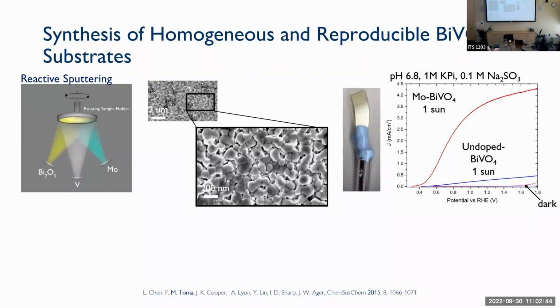So if you don't have any doping, you have kind of a very sad and flat curve. But then if you dope the material with molybdenum, then you see a shift in the onset potential. And this is really important because it tells you the operating voltage of the material. And then you see also an increase in the current density, which is also another factor that tells you that the material is performing well.